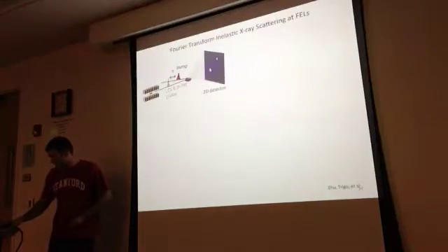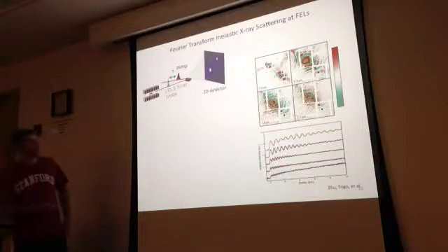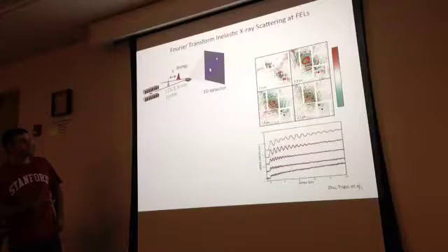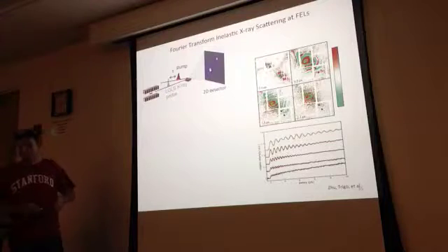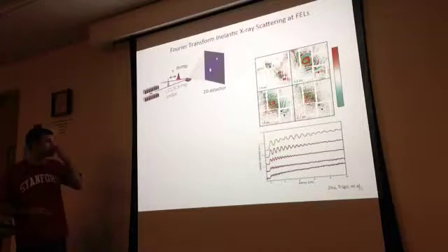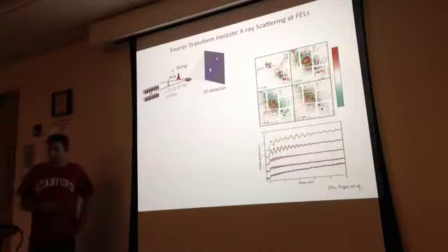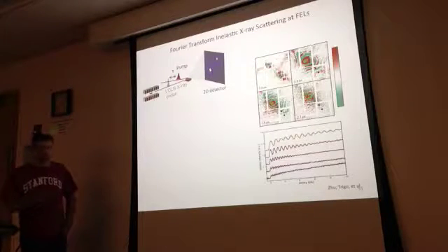Okay, so again, in this movie I was just showing you, if you pick individual pixels, so for instance this yellow pixel and then these darker and darker red pixels, you'll see that the intensity is oscillating like this, and the pixels closer to zone center, like this yellow one, are oscillating slower, whereas the higher and higher wave vector ones are oscillating faster. And so we're really seeing the phonon dispersion here. This data is germanium, the last slide was gallium arsenide.